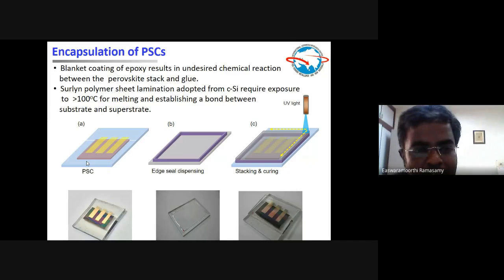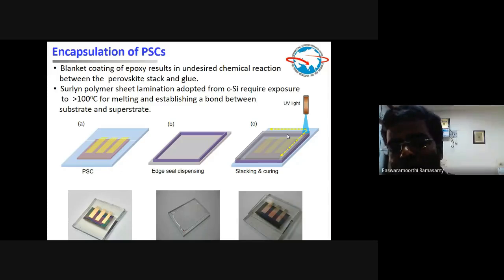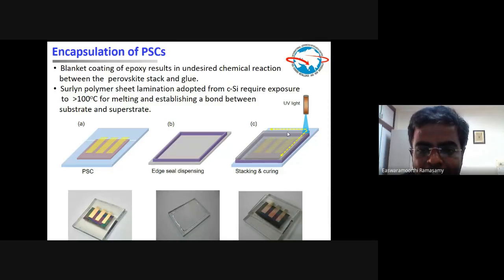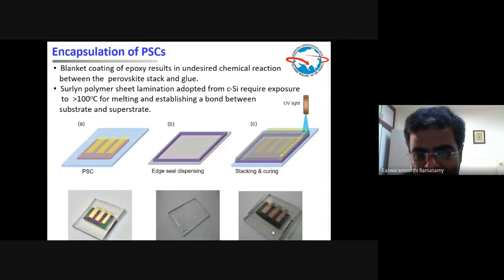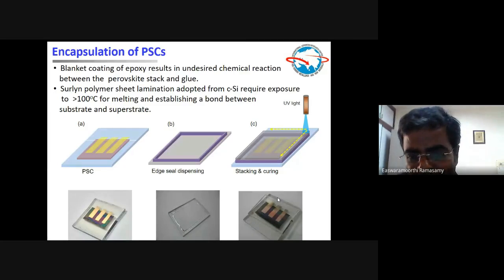This is a typical solar cell shown in the previous slides, this schematic. We made edge sealant by using a UV glue, and then glass was used as a cover because it has a very low water and oxygen permeability ratio. So we used a selective UV light to glue this glass to the plates with the help of UV epoxy glue. You can see the pictures indicating the corresponding stages. So this is the laboratory scale encapsulated device.